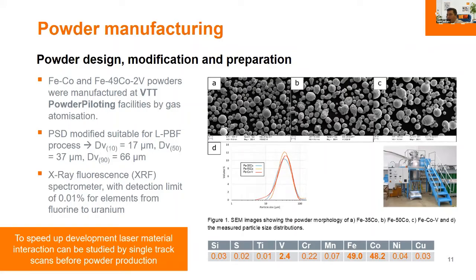And of course, if you think about what it takes to make one batch of atomization in the laboratory pilot scale, make all these analyses of the powders, and then do the first printing experiments, I would say that 1 week is the minimum. Typically it takes 1 to 2 weeks to make that one step and to evaluate the outcome of that material. To speed that up, we have developed some processes where we don't need the powder in the first stage. We utilize bulk samples and make laser studies of how the laser interacts with those materials, for example whether there is cracking or separation of phases during the laser exposure of that material.